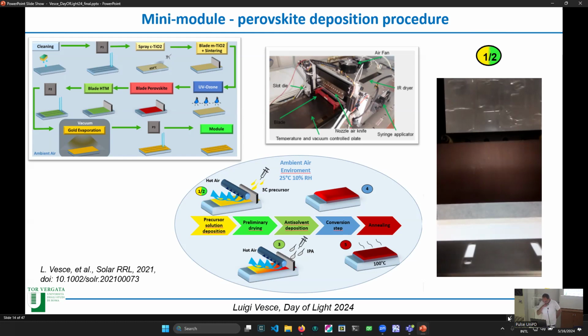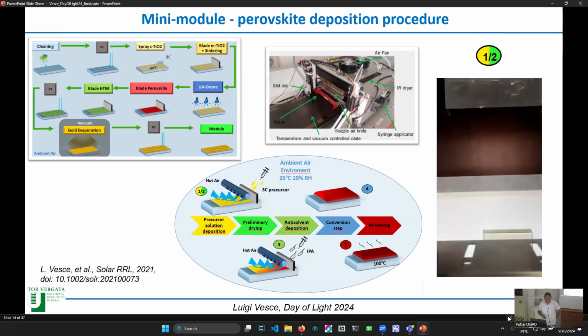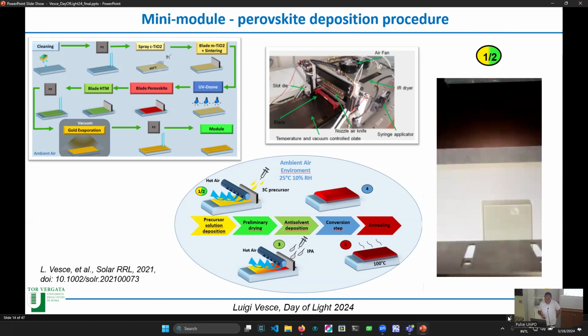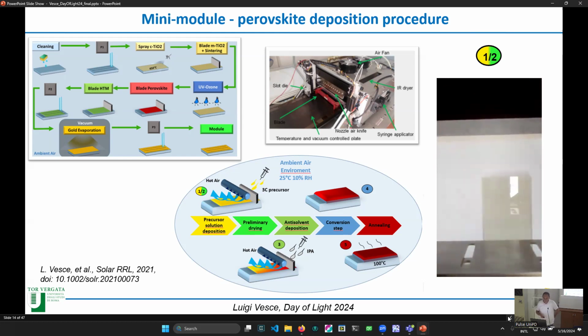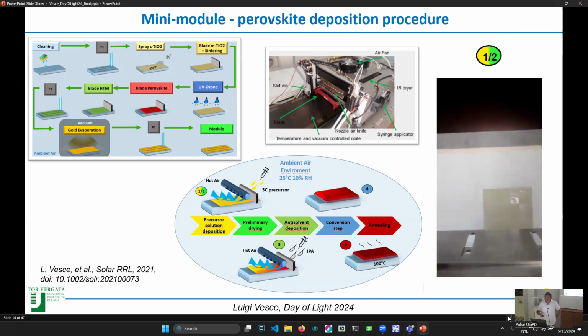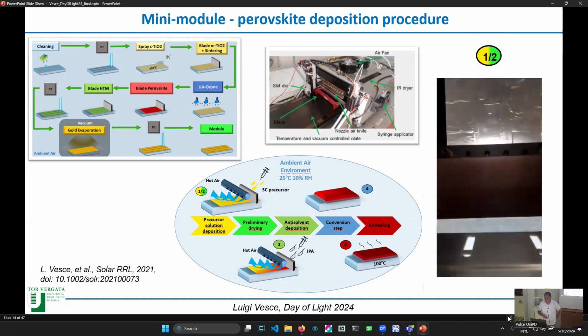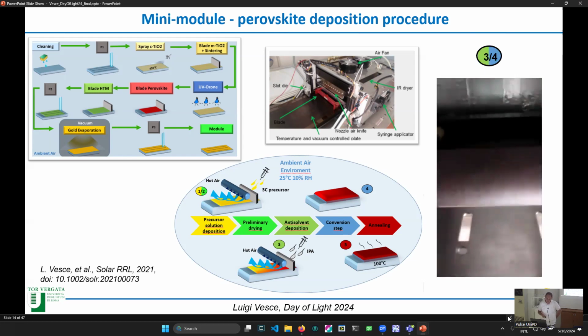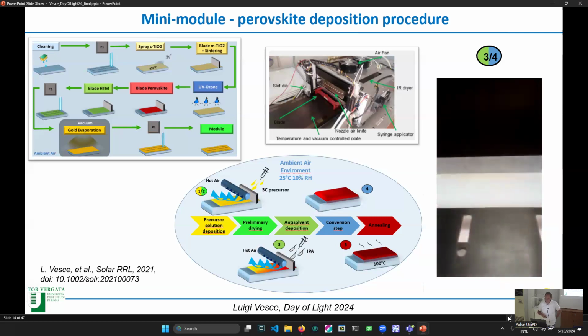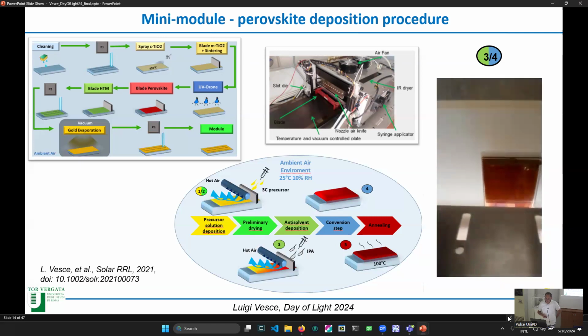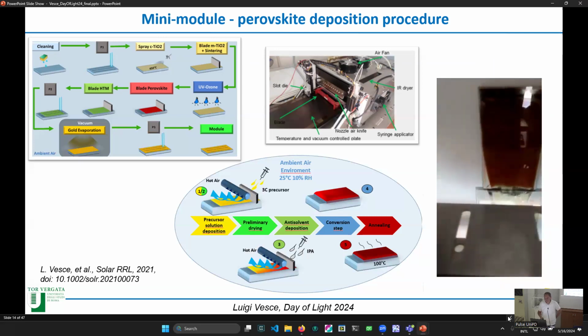The process is a one-step process. This means that first we deposit the precursor solution with the blade coater, and then we have some preliminary drying after this step, but the layer is still wet. To complete the perovskite conversion and growth, we use the anti-solvent technique. We put a solvent, in this case isopropanol, that can wash out the solvents we need for the formulation of the perovskite, in this case DMSO and DMF.